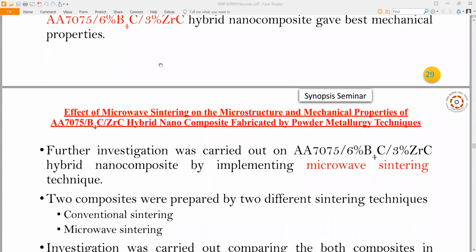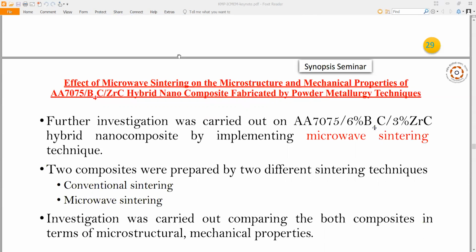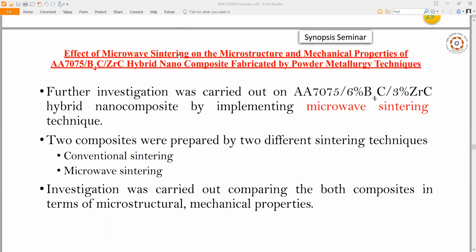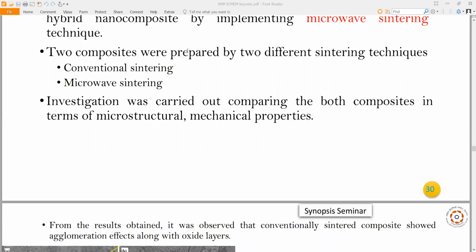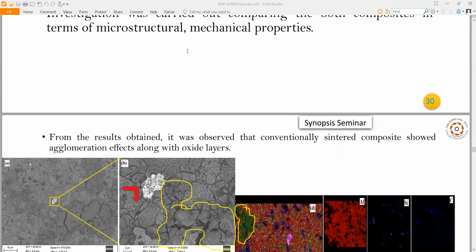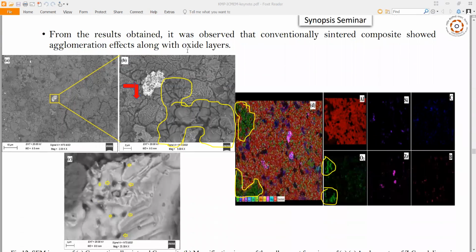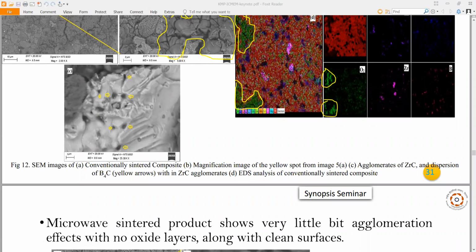Then the third objective was the effect of microwave sintering on the microstructure and mechanical properties of AA7075 B4C ZrC hybrid nanocomposite fabricated by powder metallurgy techniques. Further investigation was carried out on this hybrid nanocomposite by implementing the microwave sintering technique, and two composites were prepared by two different sintering techniques, that is, conventional sintering and microwave sintering. Investigation was carried out comparing both composites in terms of microstructural and mechanical properties. From the results obtained, it was observed that conventionally sintered composites showed agglomeration effect along with oxide layers, which we can see from figure 12.